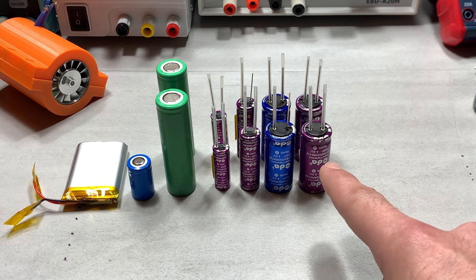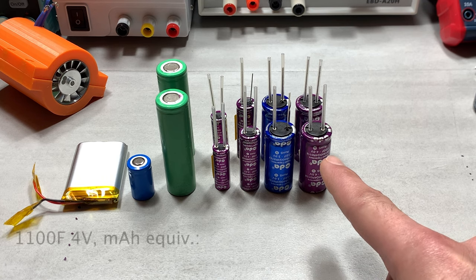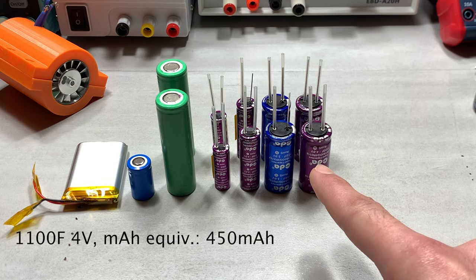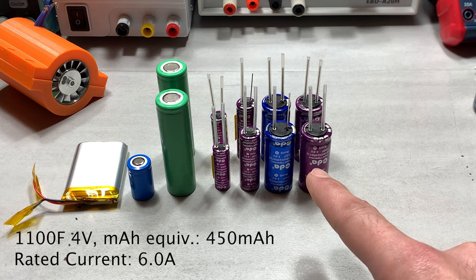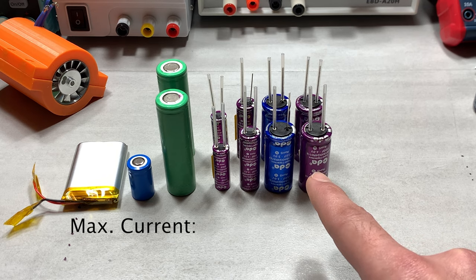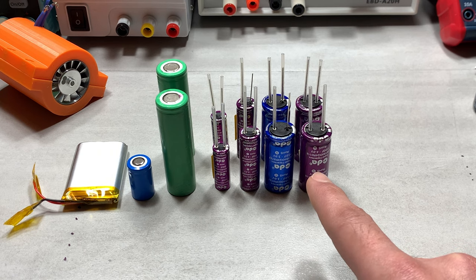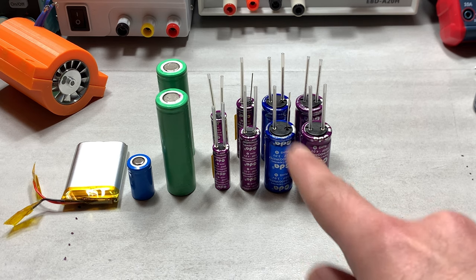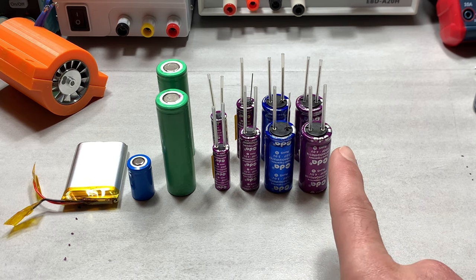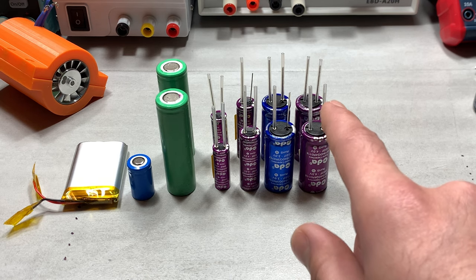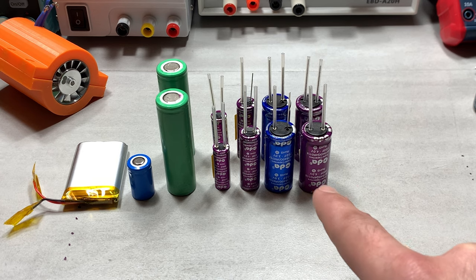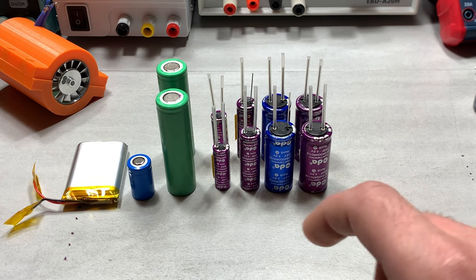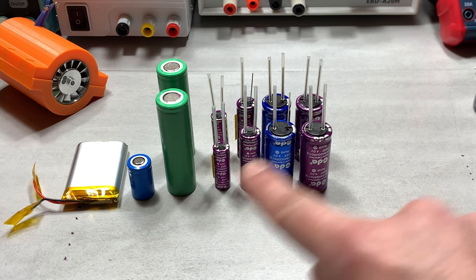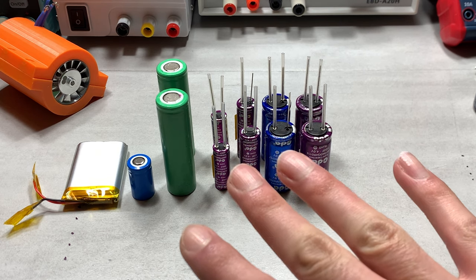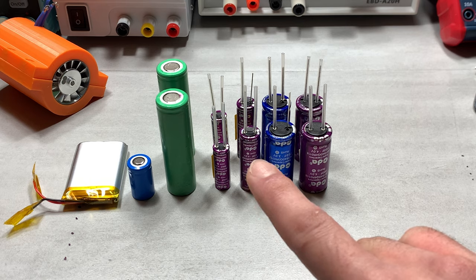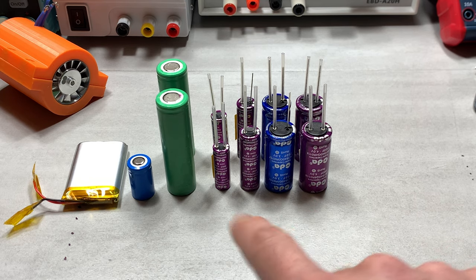So this 1.1 kilofarad 4 volt supercapacitor has a milliamp hour equivalent rating of 450 milliamp hours with a recommended rated current of 6 amps and a maximum current of 40 amps, with a mass of only about 21 grams, which is basically the same as the capacitor in Tom Stanton's video, which was only 100 farads, 3.0 volts. So this is where I begin to suspect that the types of capacitors that are of the lower energy density may be what the book was referring to as second generation, and that these ones may be third generation. Again, I am not an expert on this subject, at least not yet, so I cannot say for certainty if that is the case, but that would be my educated guess.